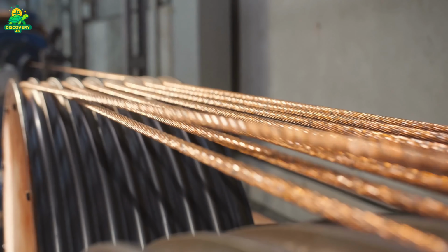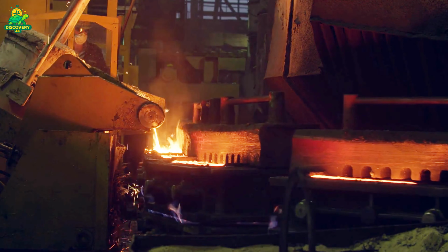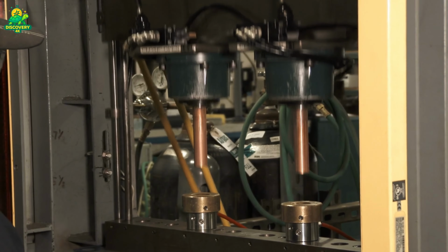The molten matte is then transferred to another furnace called a converter. Here, air or pure oxygen is blasted through the molten material. The oxygen reacts with the remaining sulfur and iron, driving them out as gas or slag. The result, a product called blister copper, so named because its surface appears blistered with bubbles of escaping gas. This blister copper is about 98 to 99% pure.